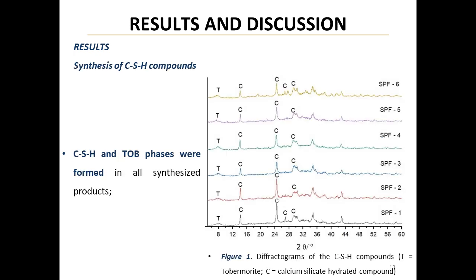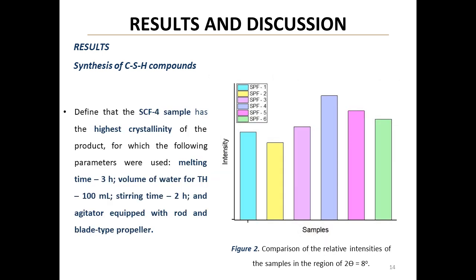The researchers successfully produced CSH and tobermorite phases in all synthesized products. This confirms the viability of their approach in transforming waste into valuable compounds. They found that the SCF4 sample showed the highest crystallinity. This sample was produced with a 3-hour melting time, 100 milliliters of water, 2 hours of stirring, and using a rod and blade type propeller agitator.